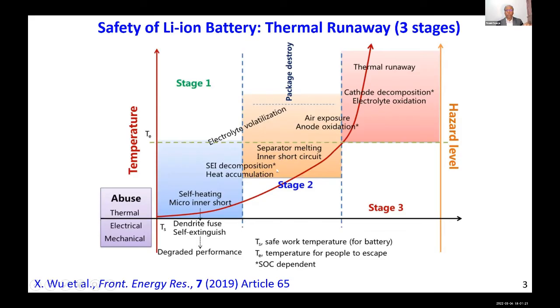If you still allow it to continue, then the separators start melting, and further the anode, which is the graphite, gets exposed to air, and then electrolyte explosion, and then fire, and then the cathode gets exploded, and then you get into the so-called thermal runaway. So you should understand what causes the so-called micro internal shorting. I'm going to take 1 or 2 examples and then explain this.